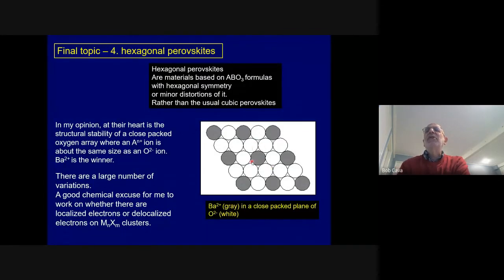You can stack oranges or grapefruits or whatever, they can form a plane that looks like this. But most oxides have only oxygen in this layer. But if you make a barium oxide, you can get barium in this layer too, because barium, which always donates 2 electrons in a chemical bond, as barium 2+ is the same size as oxygen 2-. So barium 2+ and oxygen 2- can do this, and the net result is a whole bunch of what are called hexagonal perovskites, where you can get something with an ABO3 type formula, but involving barium in an oxygen close packed plane, and the net result being triangular lattices.